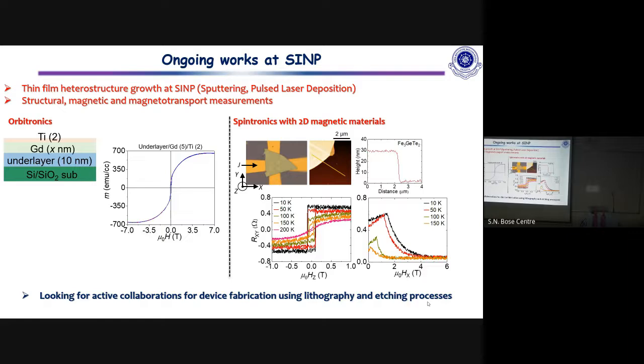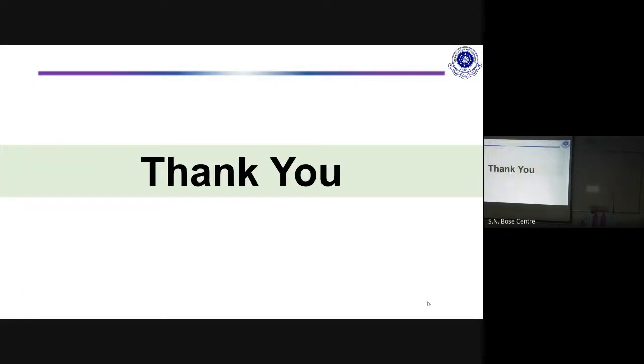The only thing that we saw is that the metallicity is still preserved, but the ordering temperature, the Curie temperature, is dropped down. The bulk was around 225 Kelvin, but in the thin flakes it's roughly around 200 or 195. Yeah, exactly. Okay, so that's all that I had to show. Thank you very much.